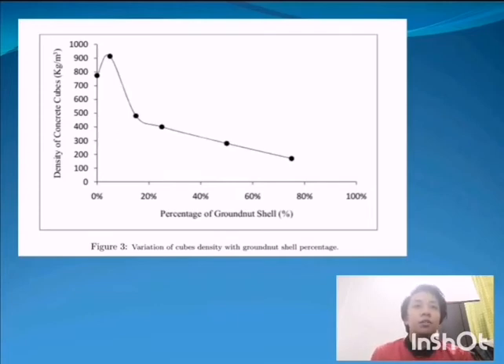Before the compressive strength test was carried out, the weight of the concrete specimen was taken to assess the density of the concrete cube. Figure 3 shows the decrease in density of the concrete cube as the replacement of groundnut shell increases, but at 5% replacement there was an increase in the density, which might be due to the fact that at that percentage replacement, the weight increased due to absorption of mixing water by the groundnut shell, thereby reducing the water-cement ratio and making the mixture denser, thus leading to a specimen of high density.